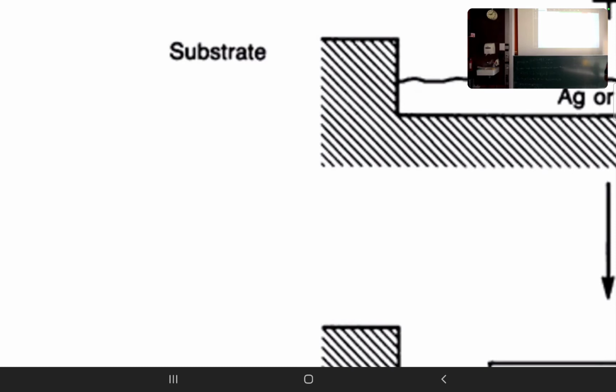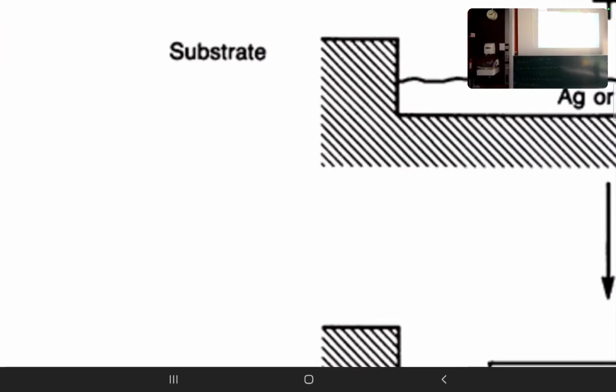It has a covalent bonding, and in that way you need something in between. And when you want to metallize silicon, you typically need a layer which sticks to both sides you would want to put together. And one of the materials is chromium. What is the other material we use as an intermediate layer between silicon and gold, or silicon and silver, or sometimes even silicon and aluminum? What do we use in between?